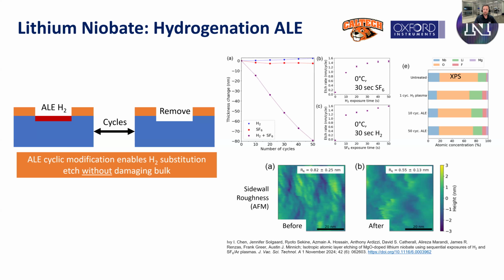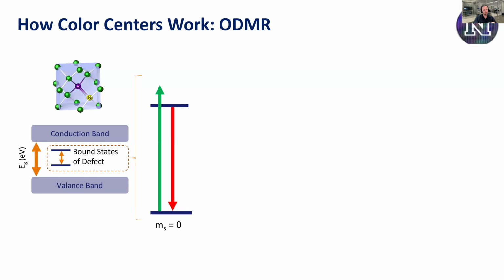Now, for those of you that don't know, color centers are super interesting. When they say diamond NV centers as an example, you actually kick out two carbons, implant a nitrogen, and you have one vacancy. It creates this bound state of the defect between your valence and conduction band, and it's pretty cool stuff. So when the spin state is zero, you put green light in, and you'll get a red photon out. You can look at that and monitor it. If you apply an RF field, you can kick this into the plus or minus 1 spin state, and now there's a non-radiative transition, so you actually see a dip in the emission.